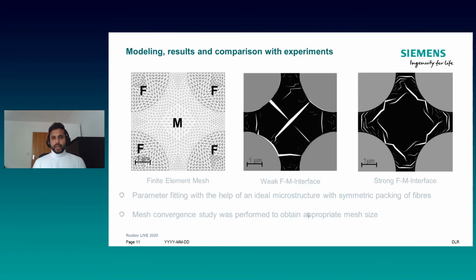Now what happens? As expected, in the case of weak fiber matrix interface, the matrix detaches itself from the fiber, as we can see in the central image. And in the case of a strong fiber matrix interface, the cracks are exclusively within the matrix. There are no cracks on the interface. So in this way, we could see that this model works and it produces results which we expect from a material with such different interfaces.